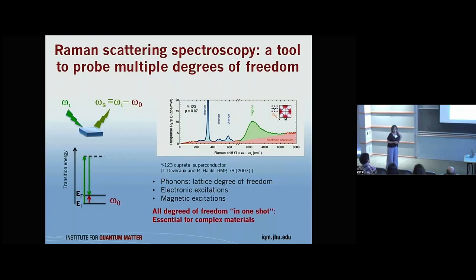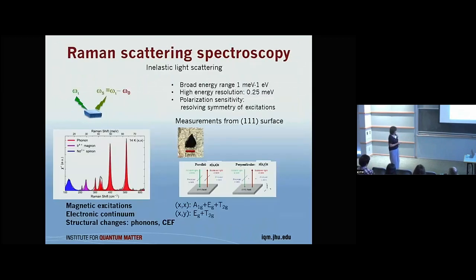One of the things I found very important is that with these new materials, there are sometimes inconsistencies between different measurements, which come from things like disorder. Here, in one spectrum, we can probe lattice, magnetic excitation, and electronic excitation, which also helps to disentangle things like the quality of the samples. We were measuring this beautiful crystal of neodymium iridate, about 1 millimeter in size. We can go down to very low frequencies, and that's a consequence of the fact that, in contrast to terahertz, our diffraction limit is not defined by the size of the crystal. Because our excitation is technically visible light, we can measure very low frequency excitations in very small crystals.